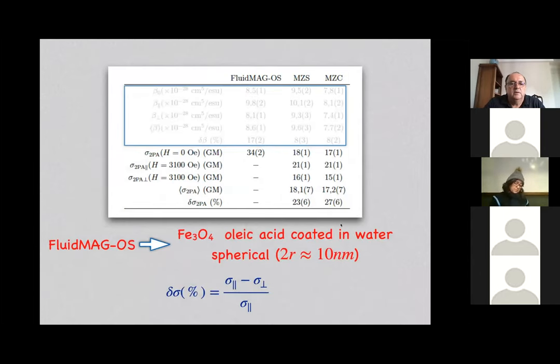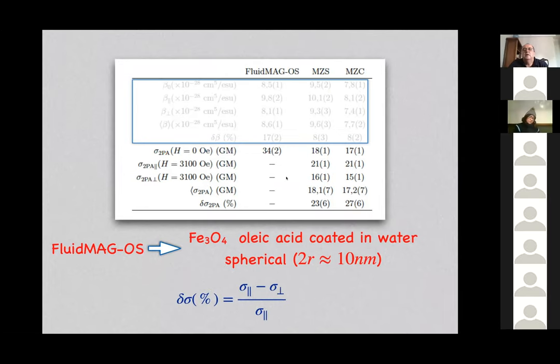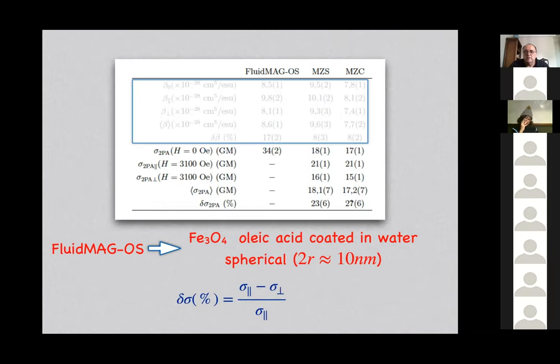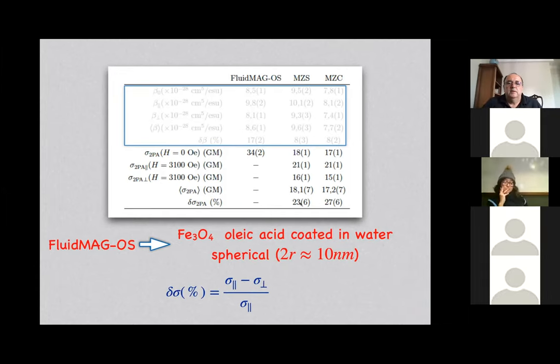Here is for the Fe3O4 with oleic acid. We have similar results here. You can see in the spherical particles and the cubic particles, almost the same, a little bit higher here, the anisotropy. We define the anisotropy this way: sigma parallel minus sigma perpendicular over sigma parallel. So the anisotropy is bigger in the cubic particles and smaller in the spherical particles, but within the error, you can say that it's almost the same parameter for the crystal. The crystal is the same, Fe3O4.